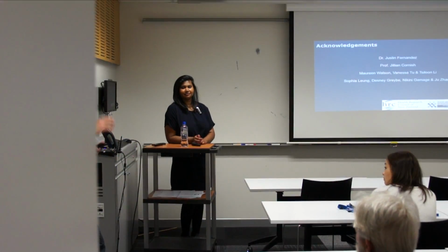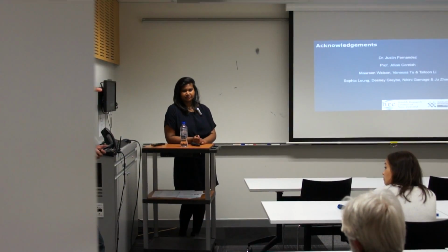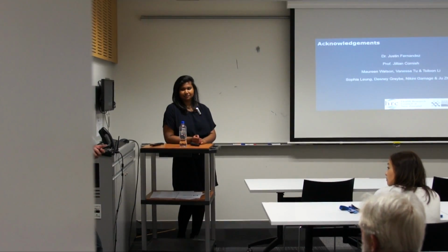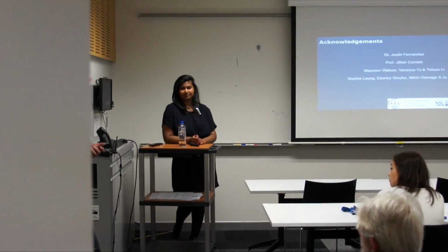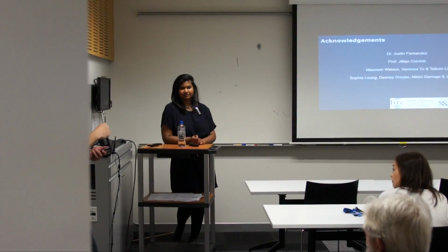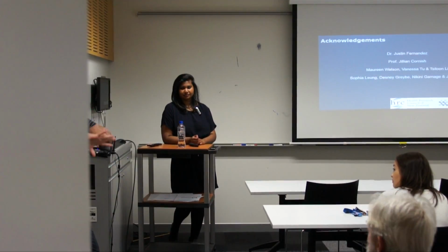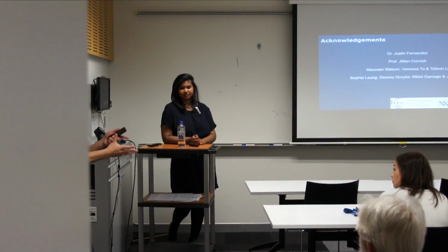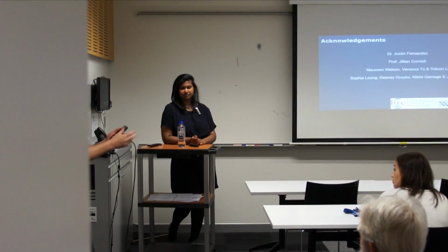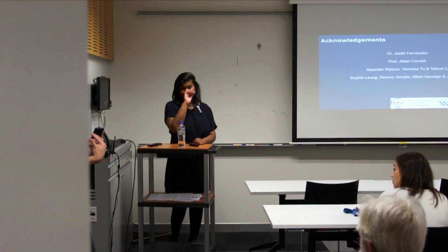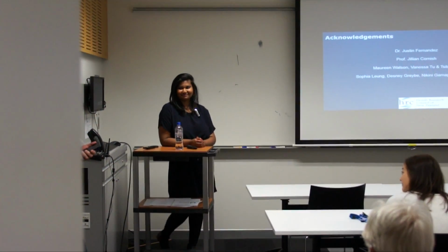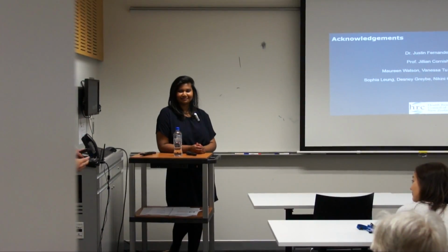Micro-CT does a good job of trying to highlight metrics associated with the geometry, but there's no good way of saying does this measure mean something mechanically. So her model was able to isolate out, and she could look at things with normalized material properties and say, I can tell you the architectural contribution to the strength is this, and then when you have the material properties, it's this, isolated out by looking at different sources: nano indentation, micro indentation, 3-point bending.